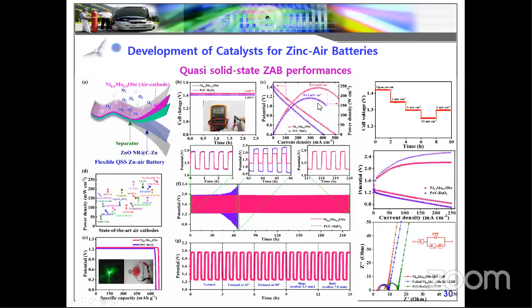commercially available materials. We also performed the rate performance of the devices. At the open circuit potential of almost 1.4 V, the cell voltage is maintained. When we increase the current, the cell voltage reduces, again increasing by 5, again 10, then again increasing by 5, it almost retained. From the studies, we confirmed our device has high rate capability. And our materials are compared with the recently reported materials.